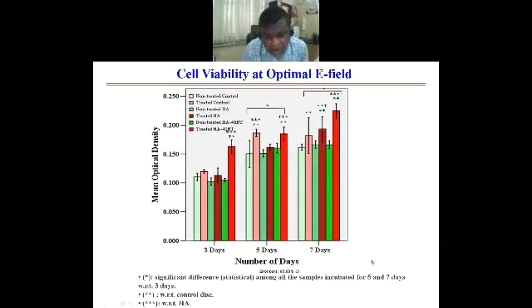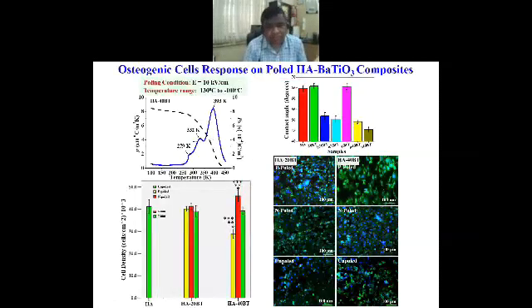And then we found that after 7 days of electric field stimulation, for hydroxyapatite 40% barium titanate, the number of mitochondrially viable cells was significantly higher than for the non-treated hydroxyapatite barium titanate, and even better than for hydroxyapatite without barium titanate and the control sample.